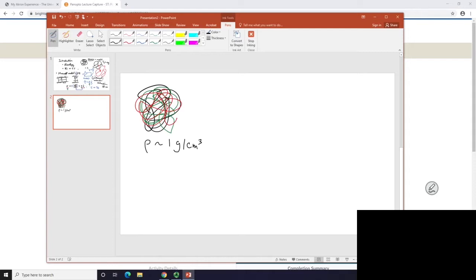All of our organic polymers have that feature. It's lightweight, and that's why our polymer is very useful, because its density is very low compared to steel, which is 7.8. You are much lighter, but you can still be strong enough, as light as water. That's our polymer. Of course, typically it's slightly less than 1. But there are polymers in the semi-crystalline state that will be larger than 1.